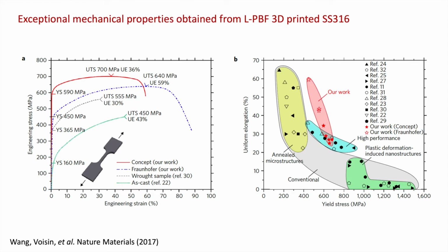They used stainless steel 316 as the model material. The green curve shows the stress and strain behavior of the as-cast SS316. The gray curve shows the wrought sample mechanical behavior. Both the blue and the red curves, they are from 3D printing. You can tell the 3D printed stainless steel 316 have better strength and ductility compared to the as-cast and the wrought samples. On the right is the classical banana curve showing the trade-off between yield strength and uniform elongation.